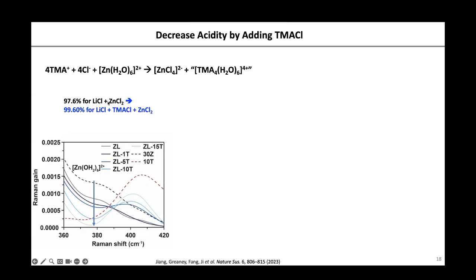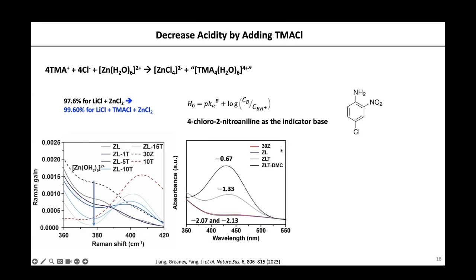Now, we increased the Coulomb efficiency from 97.6% to 99.6%. And the Raman data shows that the vibration of the hydrated zinc decreased dramatically after we add tetramethylammonium ion into the electrolyte. So for that, we also decreased the acidity. This is the purely zinc chloride solution, and that is the lithium added one.